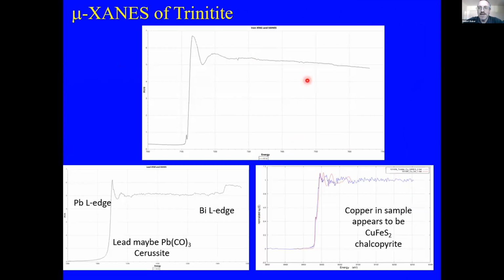But here are the micro-XANES data from some of these spots. So this is the lead L edge, and it looks from fitting the data that we have lead carbonates, which is the mineral cerussite. And in some cases, we also see a smaller feature, which is the bismuth edge. And this makes sense from the natural decay of uranium.